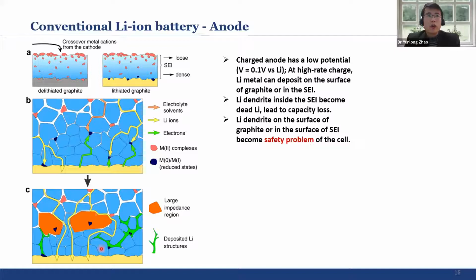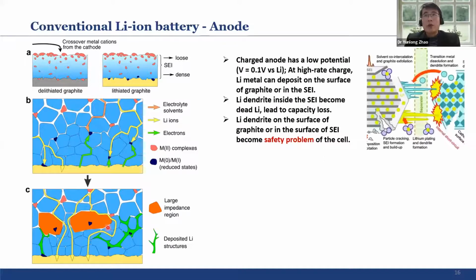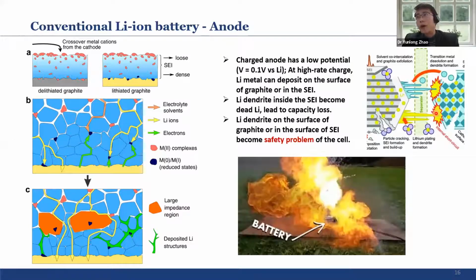Also, as I explained, the lithium will grow into a dendrite shape, which means sometimes it can grow even over the separator, from the anode side all the way to the cathode side, which means the battery will be shorted internally. Because of that, the battery will probably have problems, especially if we are using an organic electrolyte. It has the potential to catch fire.